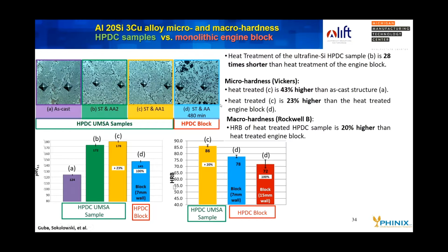If you look at the macro hardness, this is a Rockwell B hardness. You can see that the Rockwell B hardness for the artificially aged sample C is 20% more than the block material for the thicker portion of the wall, and you can also see that even for the commercial material, the hardness depends on the cooling rate, because the thinner portions of the wall are harder than the thicker portions. So you have an improved hardness at 7 millimeters and 15, but the new material is 20% harder than the commercial material.